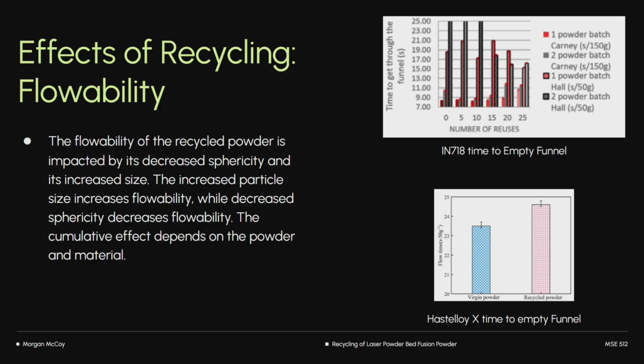On the top right, we have a chart for Inconel 718, which, depending on the test, shows both an increase and a decrease for each test based on number of reuses. And at the bottom, we have an alloy of steel, and you can see an increase in flow time.